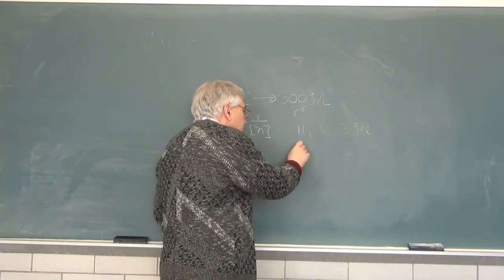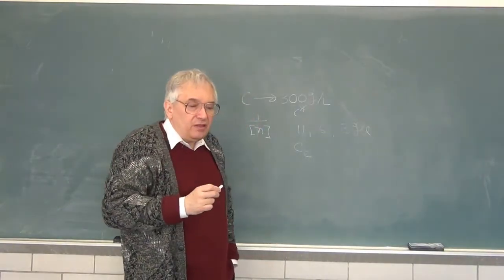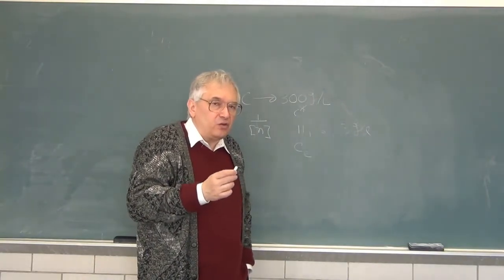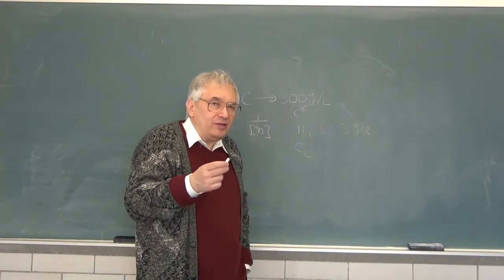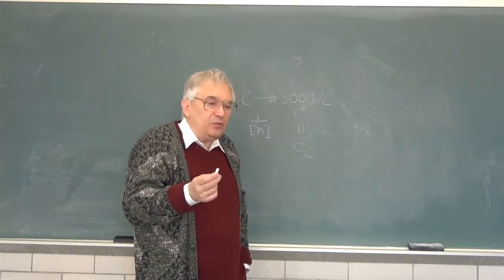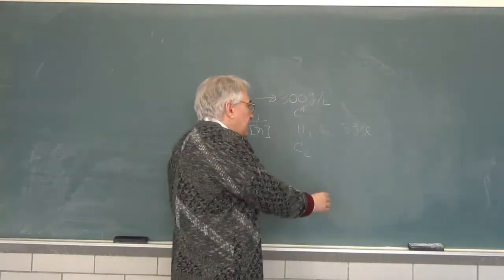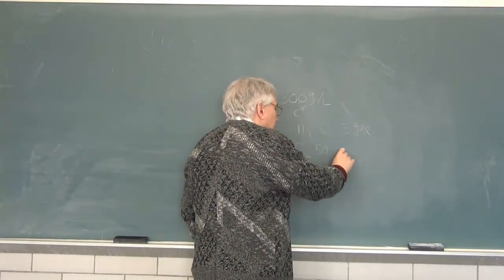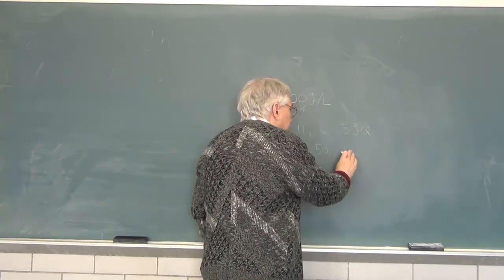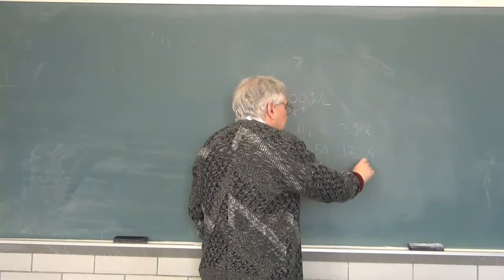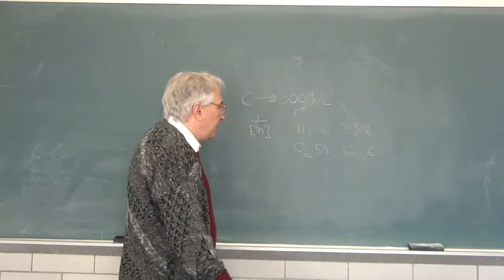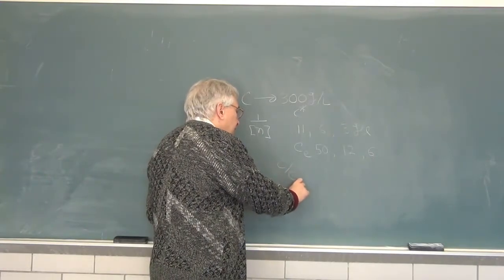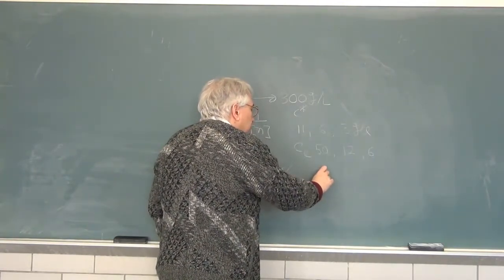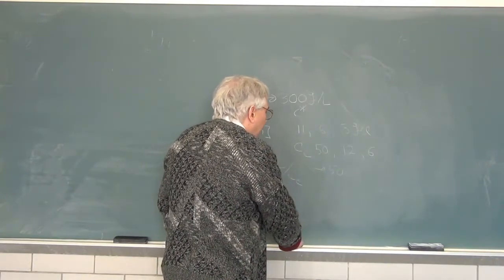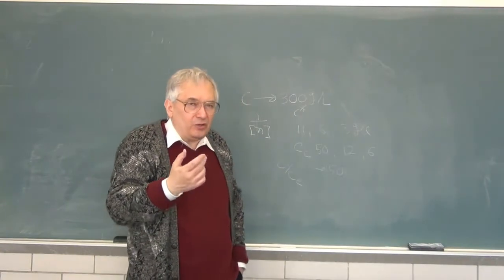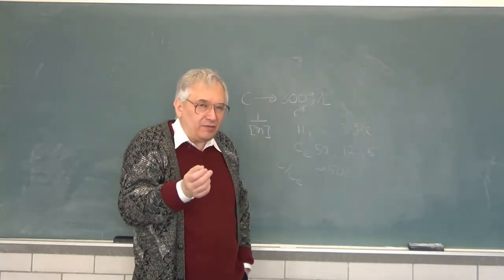And therefore, they estimated the entanglement concentrations, the concentrations at which the polymer chains have intertwined with each other, so you have what the de Gennes model would call a semi-dilute polymer solution. They estimated C_e as 50 for the small polymer, 12 for the intermediate polymer, and about 6 for the large polymer, meaning they got up to C over C_e for the largest polymer up to something around 50.